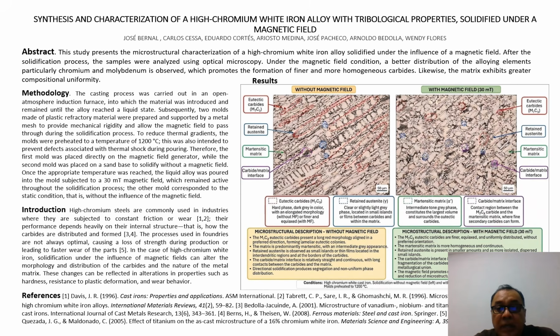Under the magnetic field condition, a better distribution of the alloying elements, particularly chromium and molybdenum, is observed, which promotes the formation of finer and more homogeneous carbides. Likewise, the matrix exhibits greater compositional uniformity.